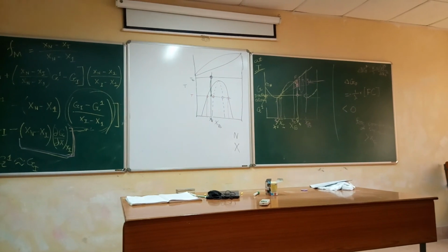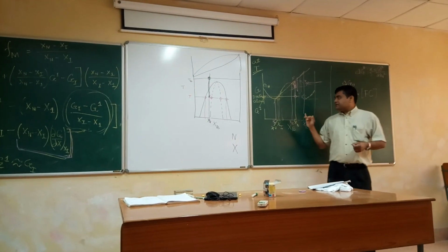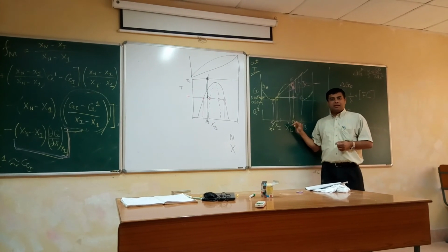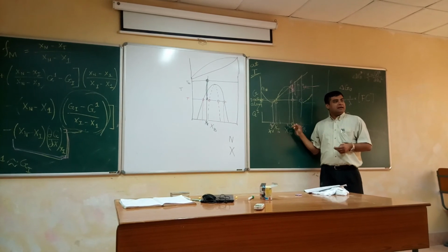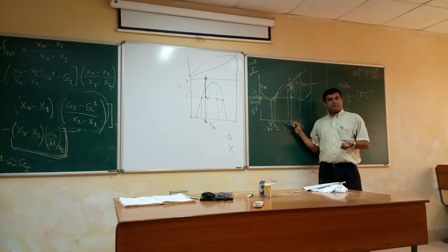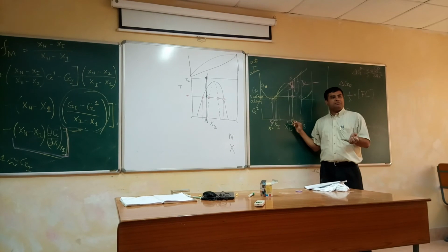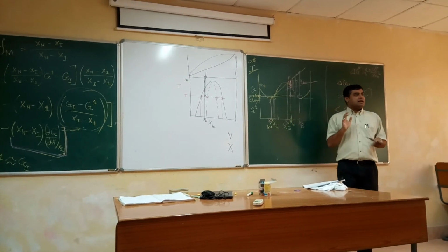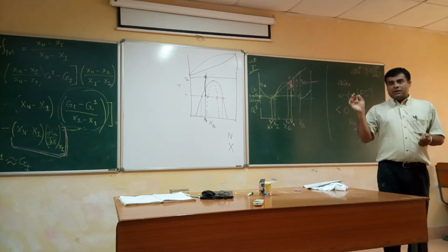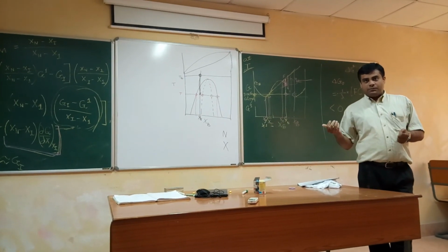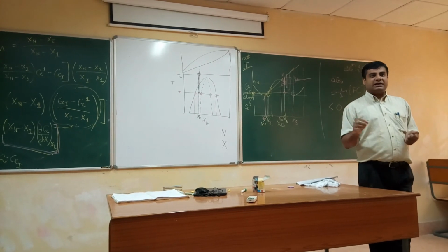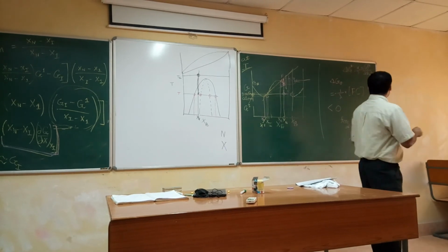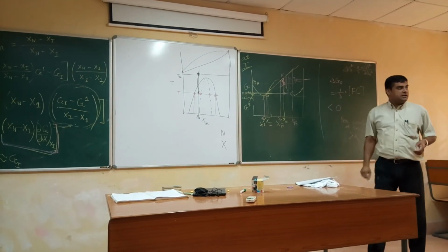It may be the case that gamma has a very low value for a certain composition away from X beta, which will take care of the decrease in the value of delta GV, even though you are away from X beta. So a certain metastable composition, not the stable composition, can have the highest nucleation rate, because then delta G star will be lowest.